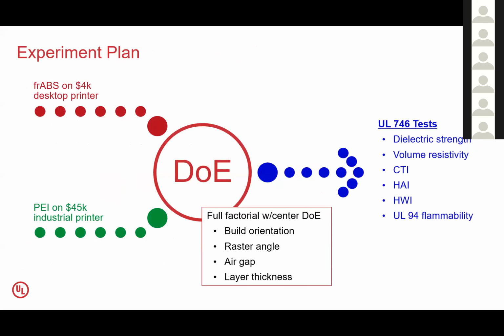To provide an overview of our research, we focused in on two materials that we could find. We found a flame retardant modified ABS material that was marketed as being a V0 rated material. And we looked at a $4,000 desktop printer for printing that material. We also looked at polyetherimide (PEI), which is an inherently flame retardant material frequently used in aerospace. It requires a lot more control, not just control, but the conditions to print it are more severe than for ABS. So we looked at a $45,000 industrial printer.